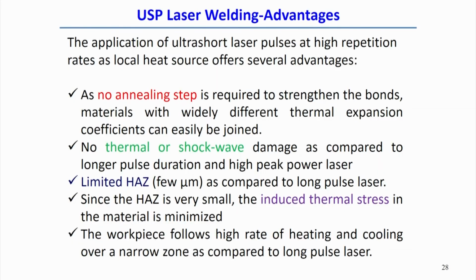mainly having two advantages. One advantage is that even the transparent glass is joined by the nonlinear absorption by the application of the ultrashort pulse laser, and the heat affected zone is localized, or melting can be localized in a very small zone. That means the overall heat affected zone is very small as compared to other welding processes, or we can say a very controlled heat affected zone can be produced by the application of the ultrashort pulse laser.